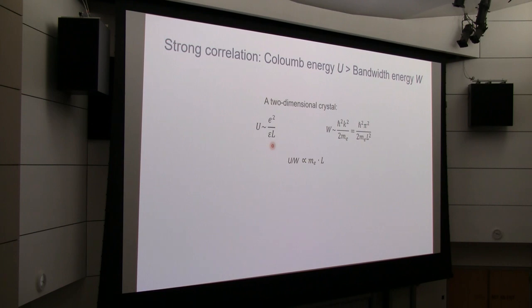And the bandwidth, as I mentioned, has the upper limit of the kinetic energy at the band edge, which scales as this form, h bar squared pi squared over 2mL squared. So the ratio between Coulomb potential and the bandwidth simply is proportional to electron mass multiplied by the length. So what this tells us is if you can create a larger and larger lattice size L, you always get a strongly correlated system, as Mott predicted.